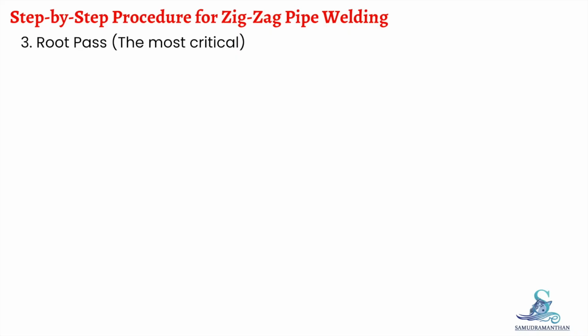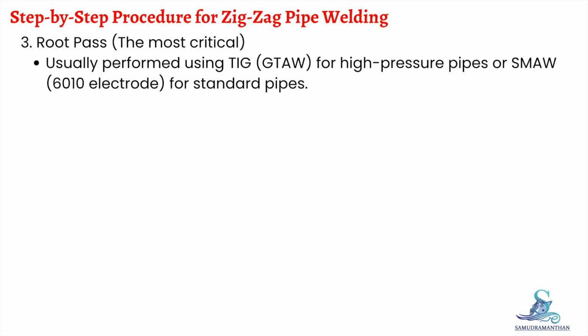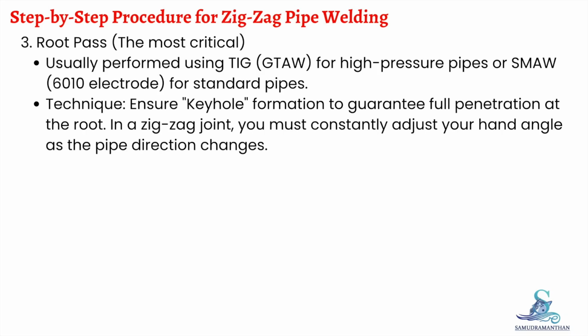Root pass, the most critical. Usually performed using TIG, GTAW, for high-pressure pipes or SMAW, 6010 electrode for standard pipes. Technique: ensure keyhole formation to guarantee full penetration at the root. In a zigzag joint, you must constantly adjust your hand angle as the pipe direction changes.